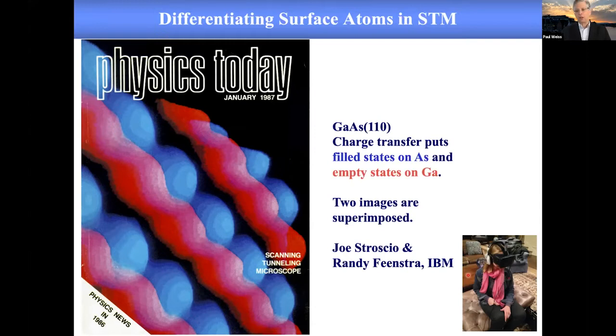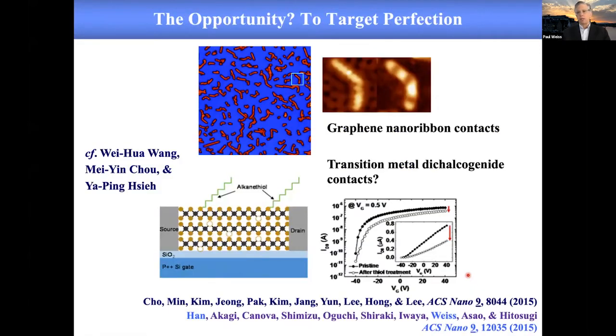Now, one of the things that was a motivator for the talk today and the work today is the following. So in these extraordinary 2D materials you've been hearing about since the first one of these lectures, one of the difficulties is how do we contact them? And let's just take graphene as a nice example, because we're able to image it with our microscopes. We're able to do specific chemistries, as you'll see, to build or to grow it. And so in the case of graphene, the common ways to make contacts are either to evaporate metals on it, which ruin its extraordinary properties, or to oxidize it, breaking its conjugation, and then reduce it back a bit. And again, we've lost the key properties that we were after in the material.